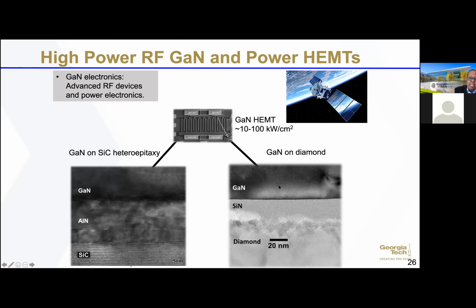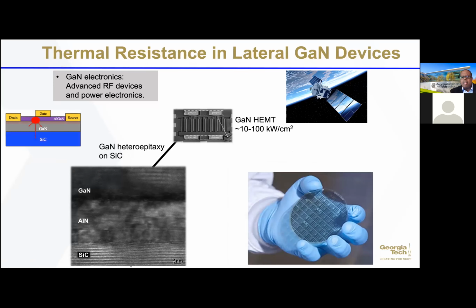But again, this lattice mismatch says that I have to put something here in order to be able to do some sort of growth, to have these come together, because I can't grow the gallium nitride directly on diamond and get electronic grade material. So these interfaces are going to play an important role. So one of the things that we looked at in our research is, first of all, we know that we can make high quality gallium nitride on other substrates. Can I remove that and actually bond it directly to diamond without this interlayer?